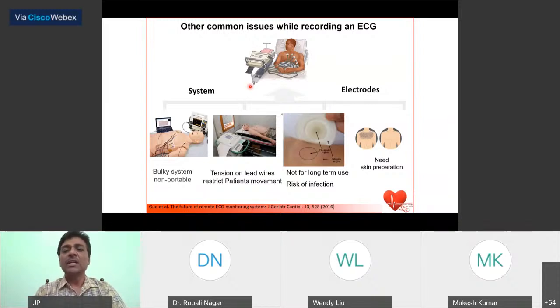These electrodes are measuring the electrical signals from the skin. Because of that, some skin preparation is needed in most cases, and we use an electrolyte gel. These electrolyte gels are used, and they use a silver chloride electrode, which is placed on the body. The problem with that, for a long time, is a risk of infection. You need skin preparation. Also, if the body moves, that creates a noise, which is known as wandering noise, and that causes a problem in the ECG signal.